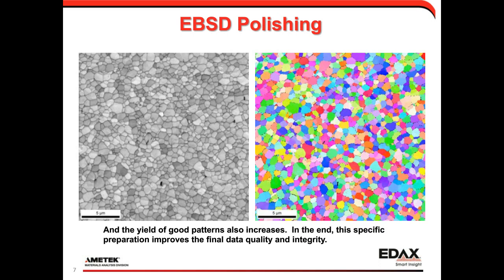And now if we look at the image quality map on the left, rather than seeing some bright areas and some dark areas, we actually see resolved grains that appear clearly. And in the orientation map, we see that nearly 100% of the points are indexed with high confidence. And this is more of what we want to get when we polish EBSD samples. We want our yield of usable diffraction points to become closer to 100%.